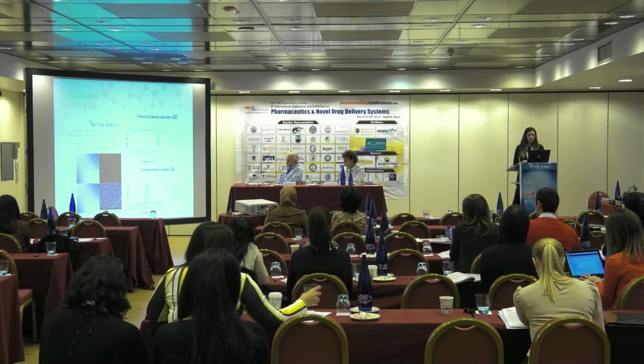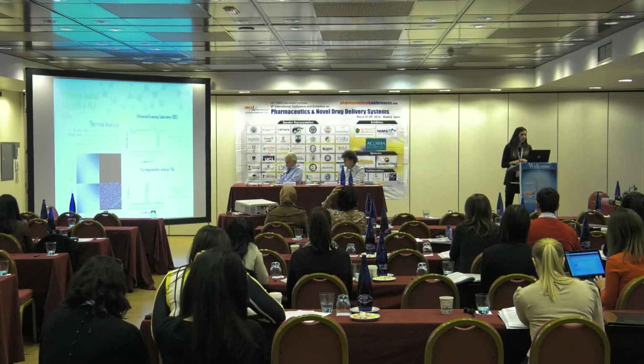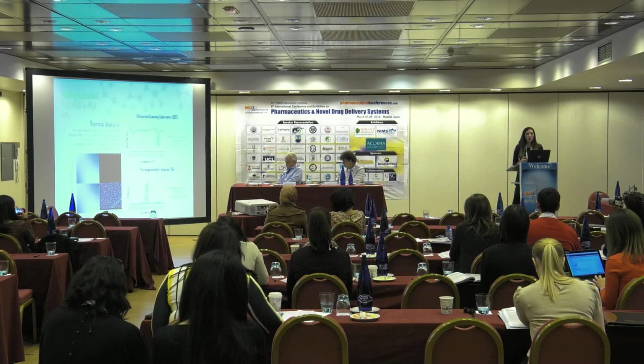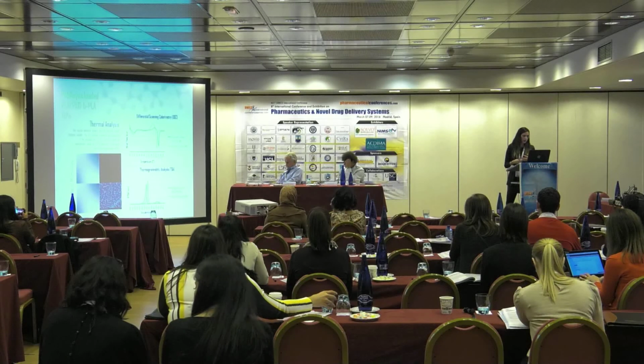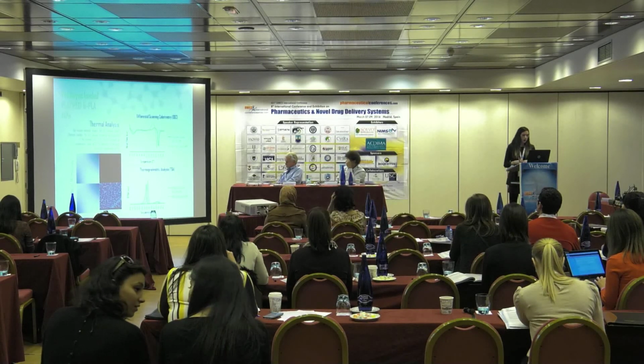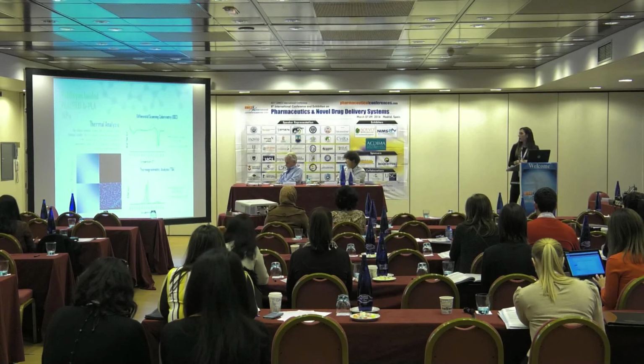Regarding these microparticles, we checked that the thermal stability of the particles was okay, and we can also observe that there was an association between the blend of polymers and the polylysine. With confocal microscopy, we also checked the presence of the polylysine in the particles as a previous study, because the polylysine was also attached to a fluorescence unit.